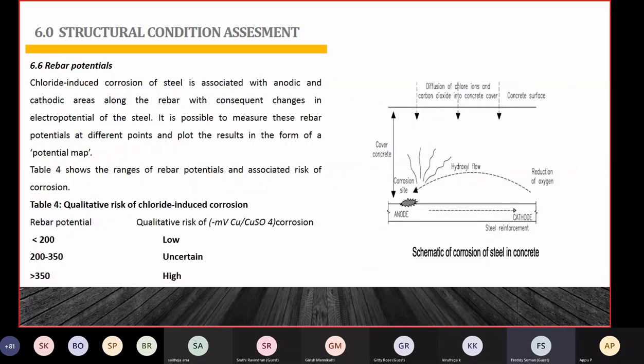Now we are coming to the rebar potential, the half cell potential assessment. This is what I told you. The reading is normally given in minus millivolt. If the reading is less negative than minus 200 millivolt, there is less chance of corrosion. We say about a 5% chance, which is very uncertain. Okay. If it is between minus 200 and minus 350, there is a 50% chance of corrosion. And if the half cell potential reading is more negative than minus 350, there is more chance of corrosion. There is a 95% chance that corrosion activity is taking place in that area. The corrosion potential is high.